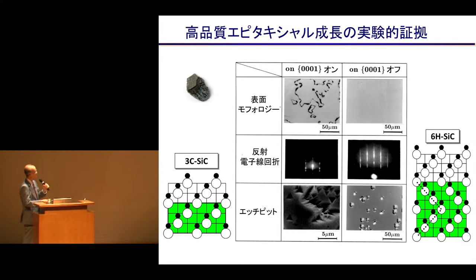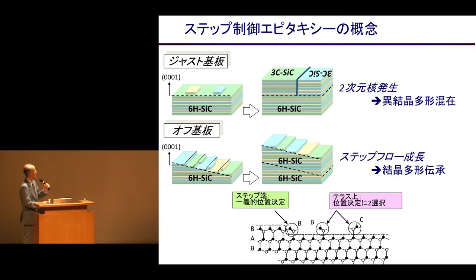So if we put it on an off-substrate and on an on-substrate, we did a comparison, and just observing the surface or looking at the RHEED, we can see that the stacking sequence is repeated on the off-substrate, but for the on-substrate side, there will be a symmetry created.